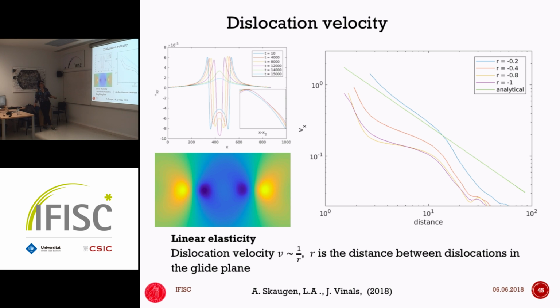And initially we see that there is some sort of equilibration, and then it gets into a regime where it does look like they approach the analytical prediction. So that means that in the case where we're close to criticality, the mass diffusion is much faster, that it actually operates almost on the same scale as the mechanical equilibrium. So the stress is kind of relaxed on that time scale. But in the other situations, we see that this is a very different case.